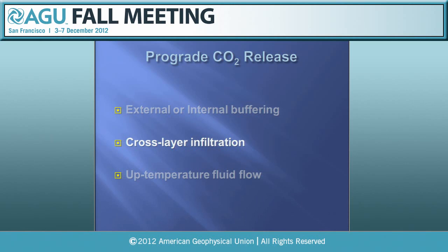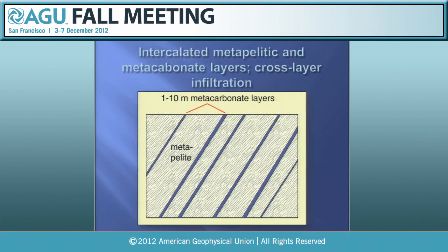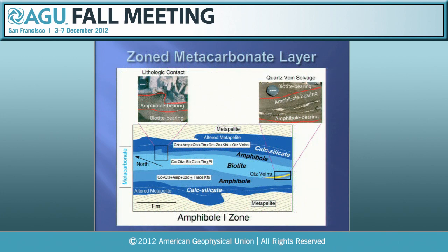So that brings us to infiltration across metamorphic carbonate layers. In the Waits River, this is very well shown, where you have 1 to 10 meter thick metacarbonate layers intercalated with metapelitic rocks. And if you zoom in and map these layers, you very often find that they are mineralogically zoned. Here's an example from the amphibolite facies. The interior of the metacarbonate layer is still fairly unreacted. It contains biotite. But then as you go to the margins of the layer, it gets more reacted, more devolatilized, amphibole is present, and then finally on the margins you have these highly devolatilized calc-silicates. So there's basically a zoning in reaction progress across these layers. So that's the key field observation here.